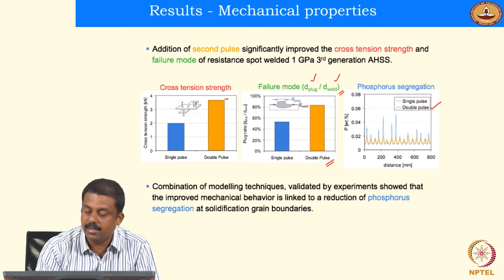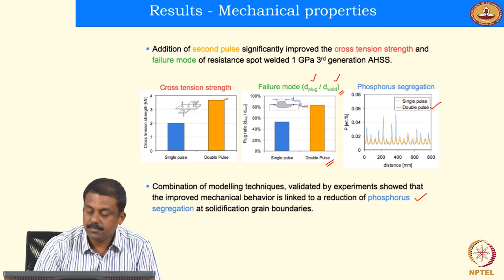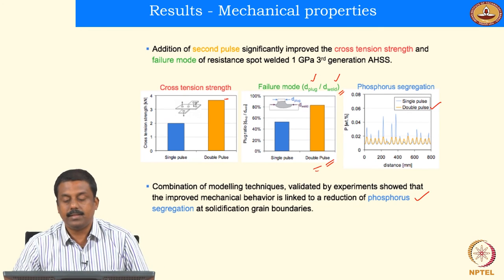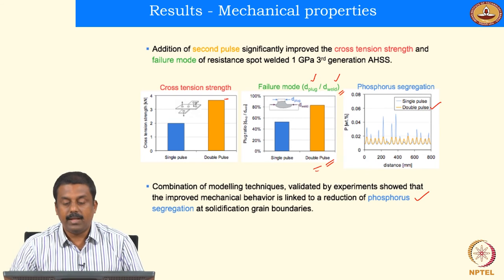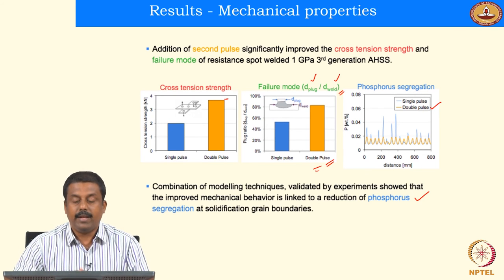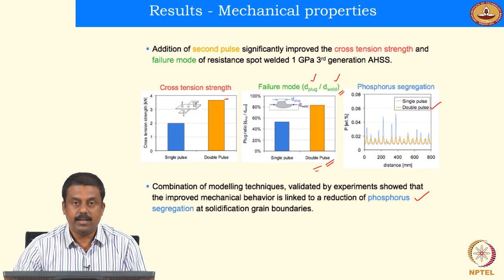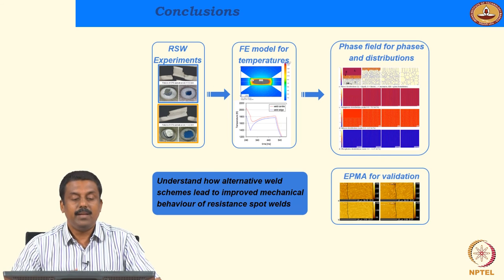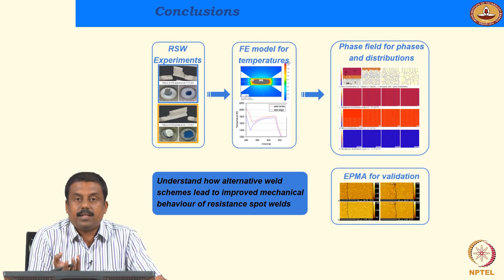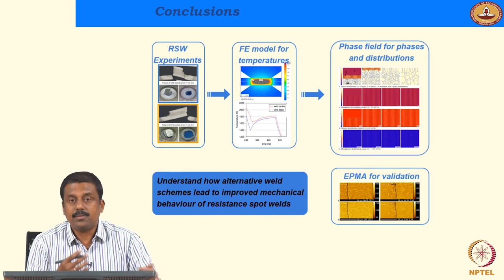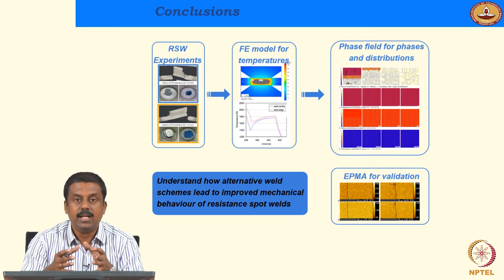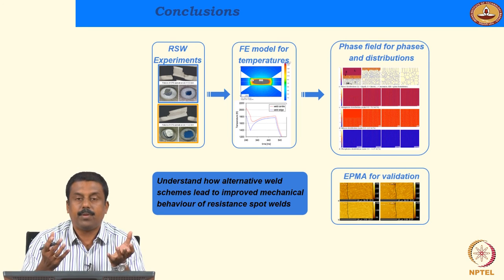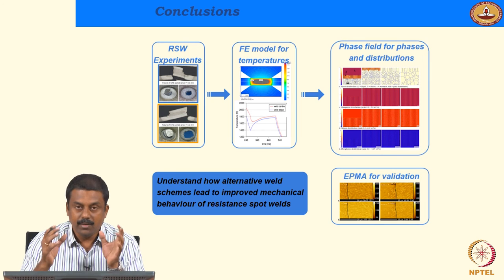So the phosphorus segregation decreases significantly at the grain boundaries at the weld center line, leading to improved mechanical properties. So you don't need to change the chemistry. By carefully manipulating the weld thermal cycle, we can still improve the mechanical properties of advanced high strength steels. That's the lesson I want to give you. And this understanding is possible mainly because of the calculations and the understanding of the elemental behavior during welding. So it's very important to understand the physics behind the process, how the segregation happens during solidification.